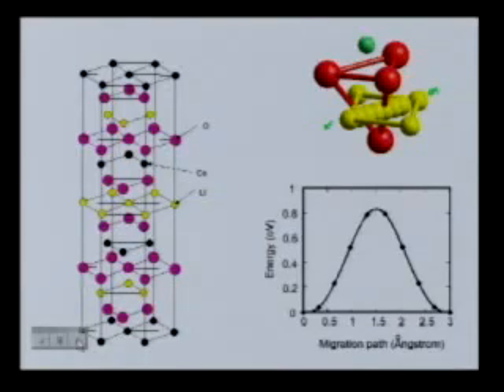If you do that in lithium cobalt oxide, you have a complication. Just to show you how the data for that kinetic Monte Carlo simulation was derived: the yellow is the lithium here, these are oxygens, the big red balls. The way you diffuse from this side to that side is straight through the oxygen bond. And if you do that, this is obtained by the elastic band method.